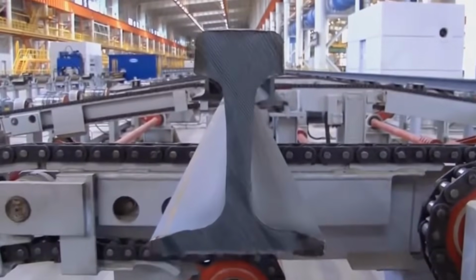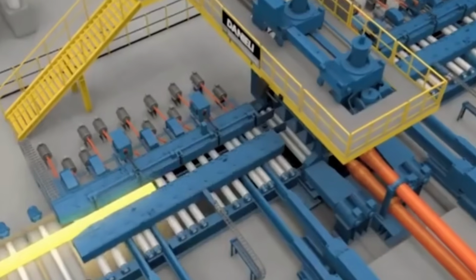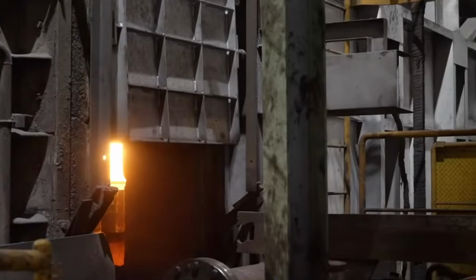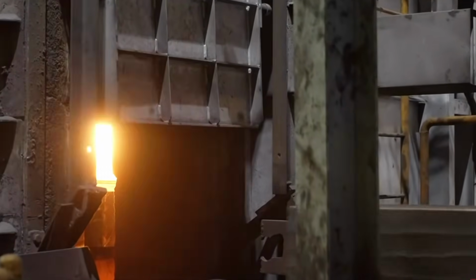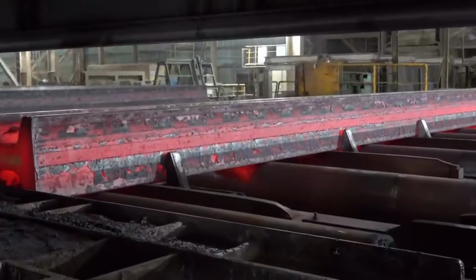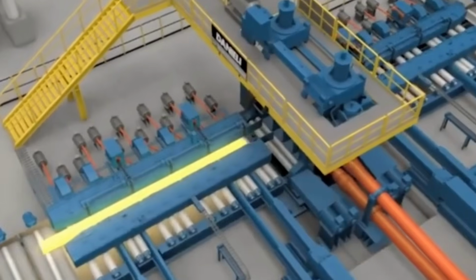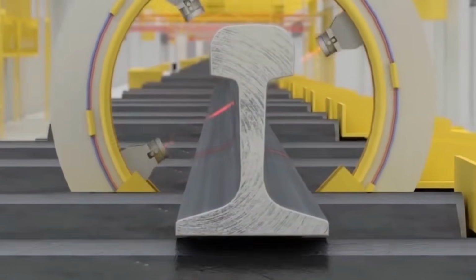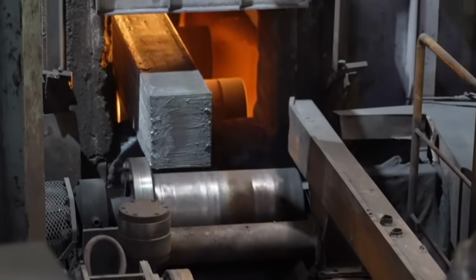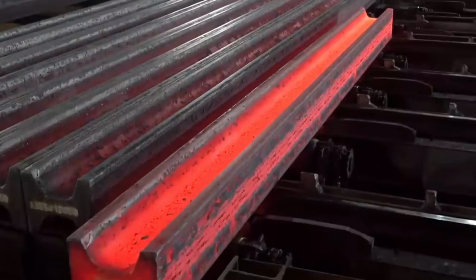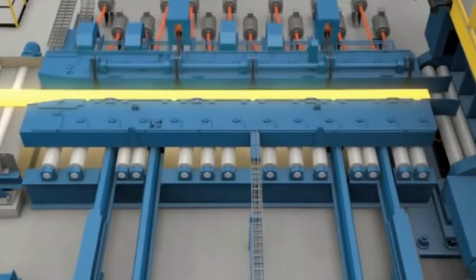Quality control begins before inspection, with operators collecting samples throughout production for laboratory testing. The quality lab crushes test pieces to measure yield strength and tensile strength, typically over 50,000 pounds per square inch. Metallurgists examine samples under microscopes to verify grain structure. Charpy impact tests measure toughness by striking notched samples with a weighted pendulum.